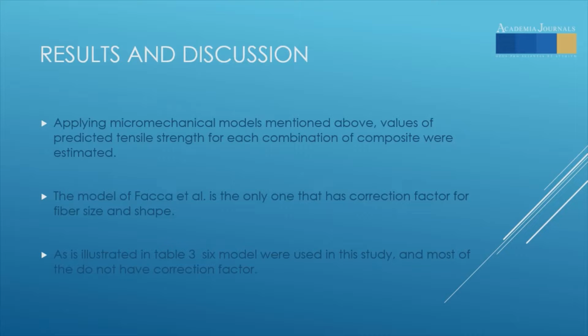The model of Facca et al., which is the only one that has a correction factor for fiber size and shape, is not really doing well at predicting values. And as we observe in table 3, most of the micromechanical models do not have a correction factor.